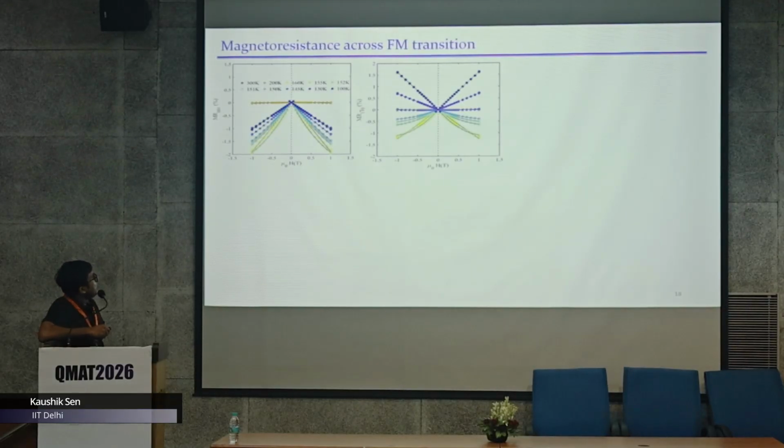and we applied magnetic field to see the resistance change. So in one direction, the 001 direction, this is magnetoresistance and this is magnetic field, and near room temperature there is no magnetoresistance. As you cool down, the magnetoresistance comes in, but if you cool down further, the negative magnetoresistance is decreasing. Okay, and also there is a curvature at the beginning, and now it's becoming linear. Now a very drastic thing happens in 1-1-0. It is negative magnetoresistance near the transition temperature. As you cool down, it becomes positive magnetoresistance, and it's even linear. Okay.